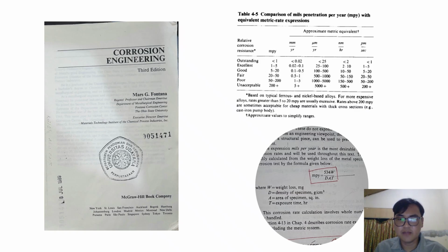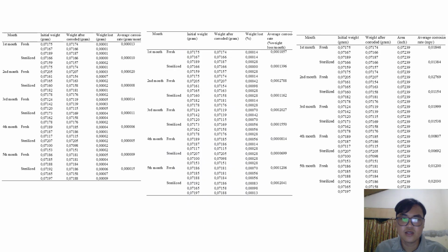The table used before and the formula used for calculating the mils per year were taken from this book titled Corrosion Engineering, written by Mars G. Fontana in 1969. This table presents our monthly data. A critical finding emerged here. The corrosion rate in the biotic environments fluctuated. It was high initially but decreased later. In contrast, the sterile environment showed a steady increase in corrosion rate, eventually surpassing the biotic rate in the final month. This phenomenon is known as a crossover.